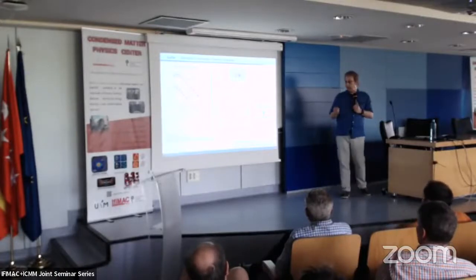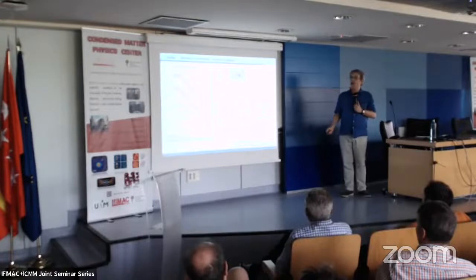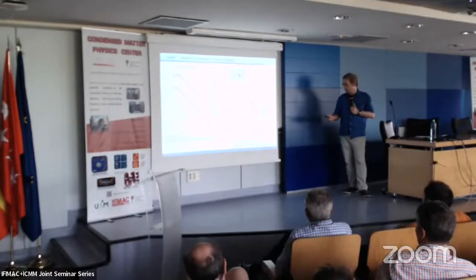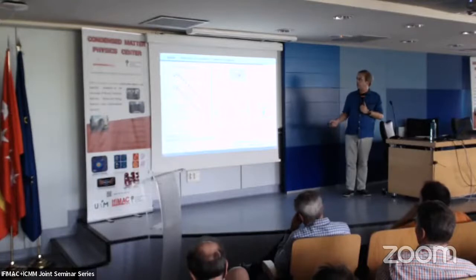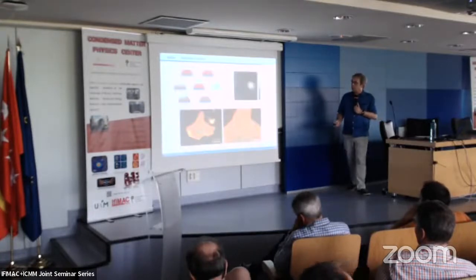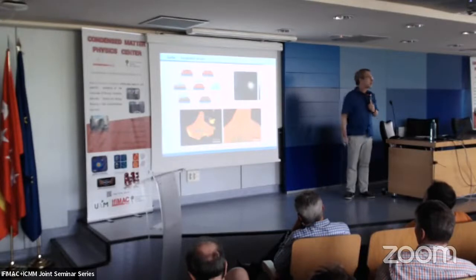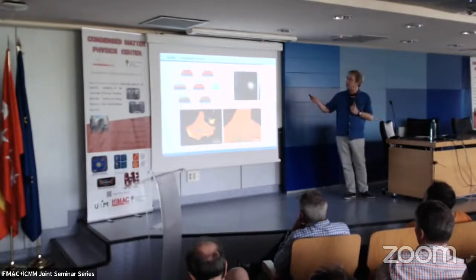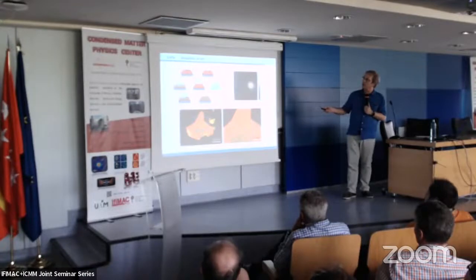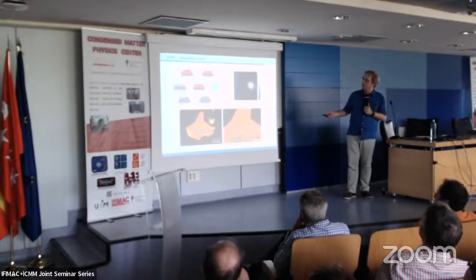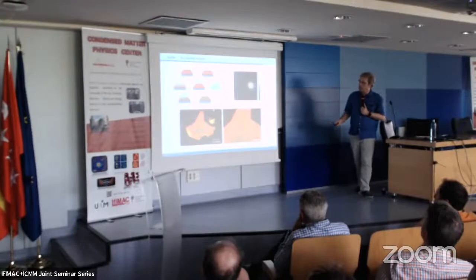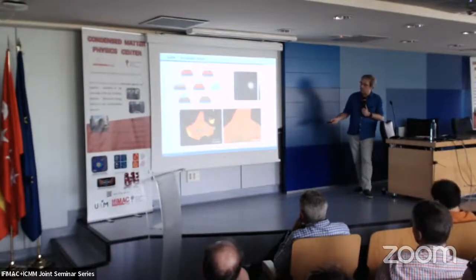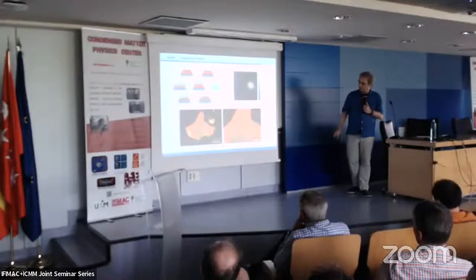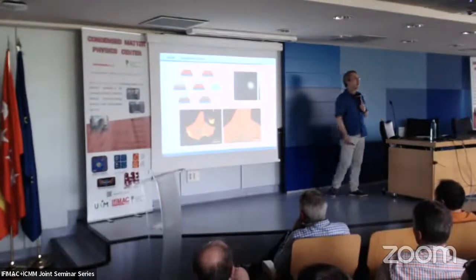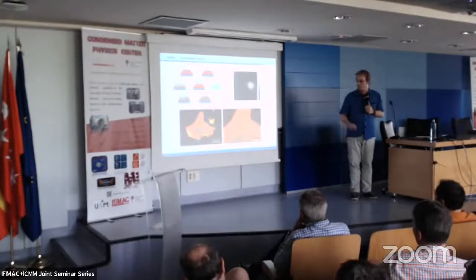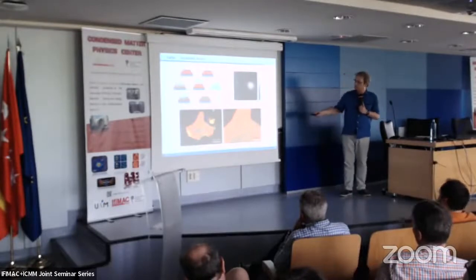But of course, 1 micrometer is very macroscopic compared to defects for emission of single photons. And so that's where the experiment started, where it's depicted here: the position of the sphere on the material, then the exfoliation of the flake on top. In optical microscope images, it looks like this, where the dots here, circled, are marked, which are spheres below the flake.